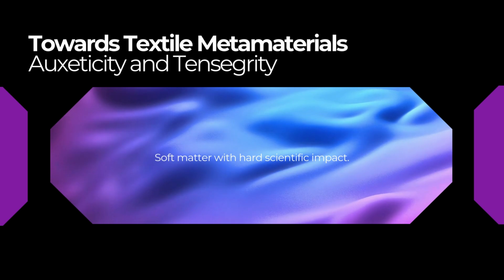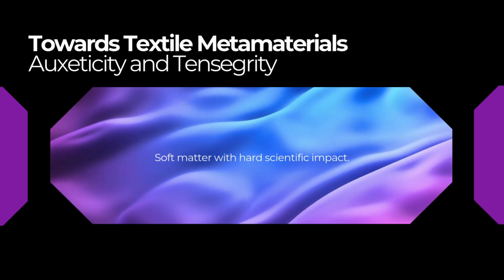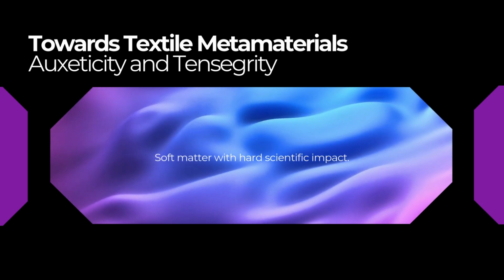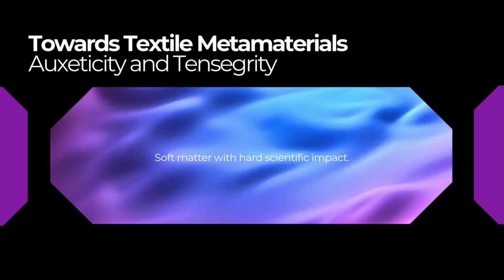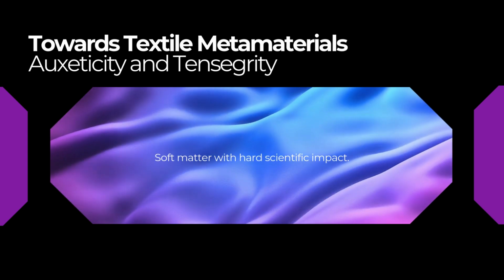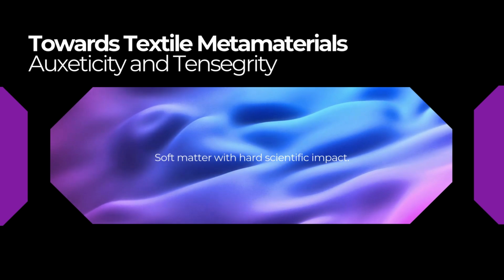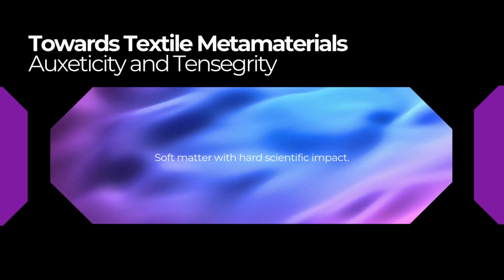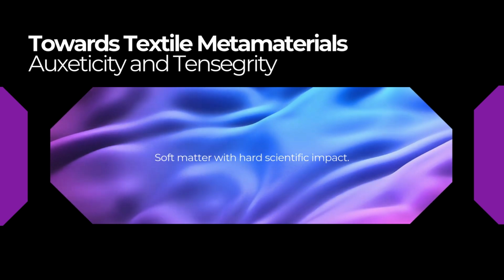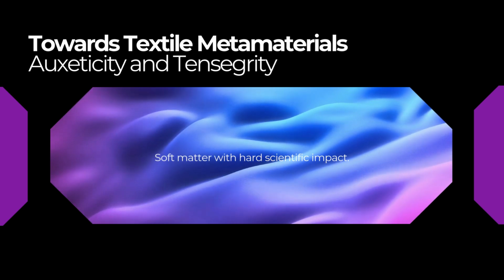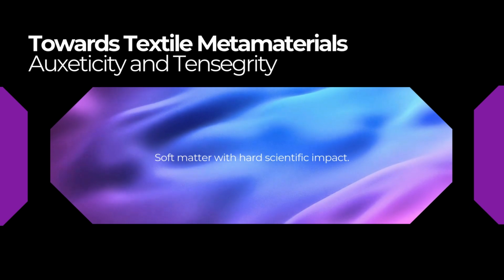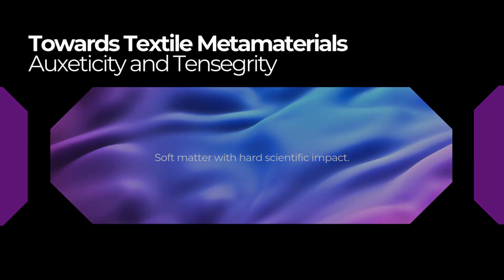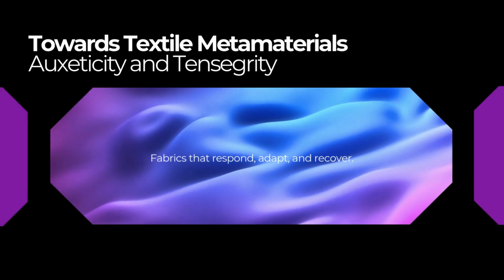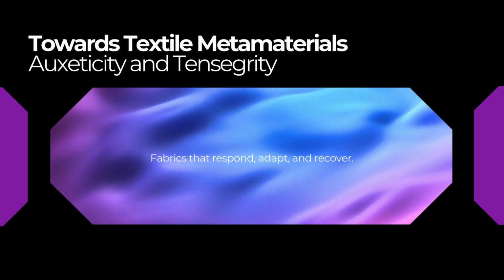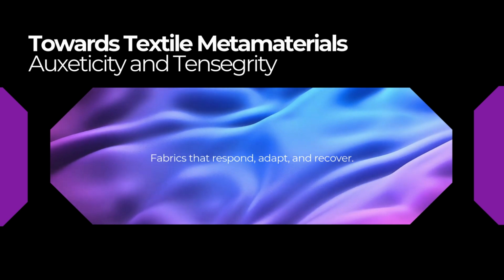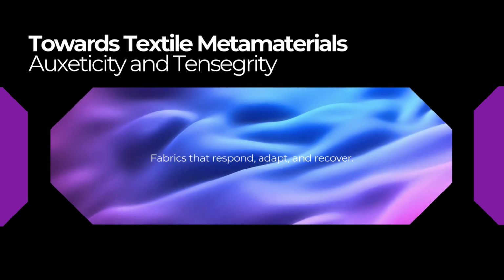And the numbers really back this up. At a defined 15% strain, get this, the average load required for the TR sample was 539 newtons. Okay. And for the original as-received sample? Only 432 newtons. That's roughly a 25% increase in load capacity. That jump confirms that the thermal treatment created more interfiber entanglement and more of those fused bonds. That's a huge enhancement. But for any practical application, the question isn't just, can it do this once, but can it keep doing it? Can it survive repeated stress?